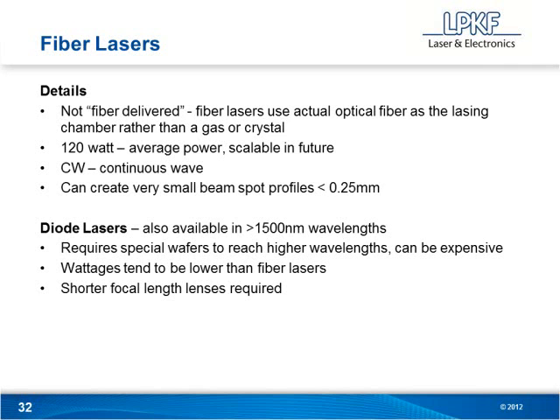Development of telecom technology in the late 90s, there were only a very small number of companies that were able to scale that technology up to industrial power levels. And interestingly enough, the first fiber laser wavelengths were in this mid-infrared regime, in the 1540 nanometer regime. Having said that, the majority of industrial fiber lasers out now are in the shorter wavelength 1070 nanometer regime, because it's even easier to build a high-power fiber laser at that wavelength using ytterbium as the dopant rather than the erbium 1540 wavelength and the thulium 1940 wavelengths that we're talking about here.